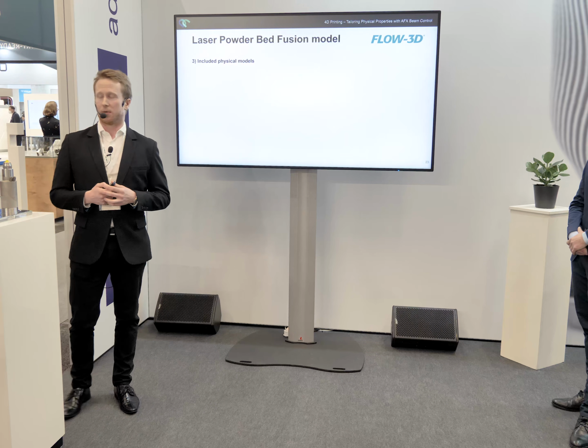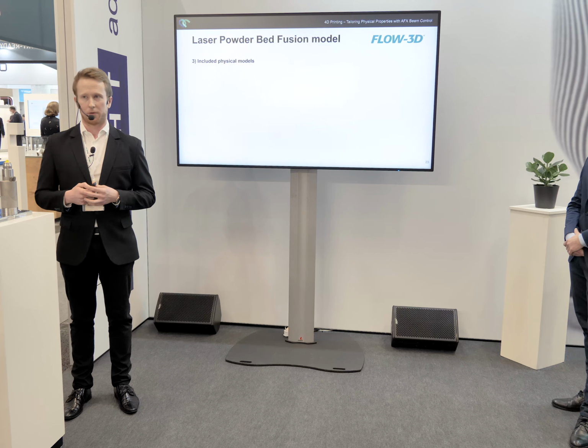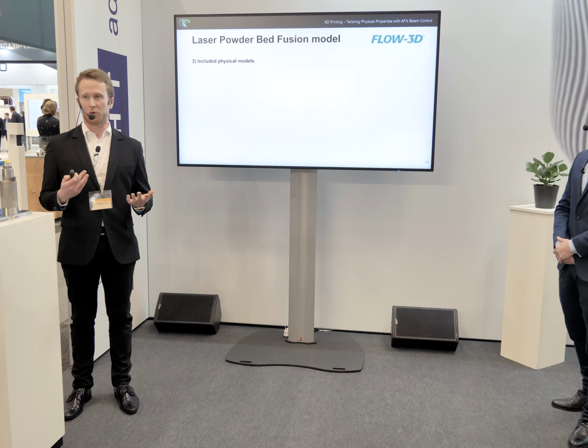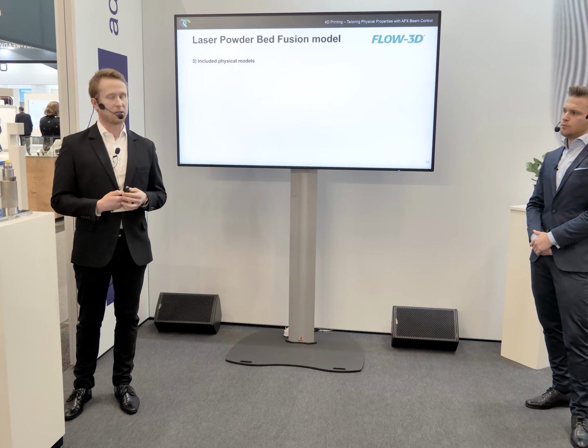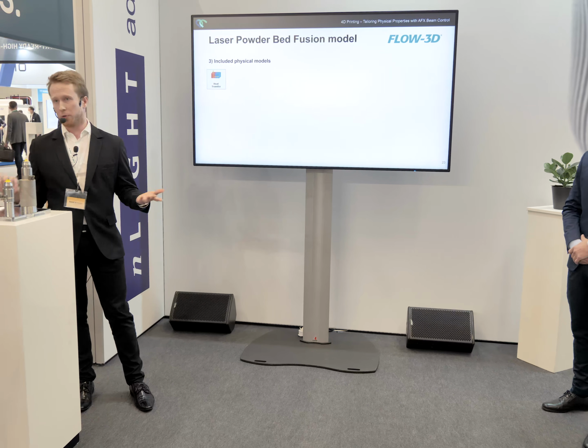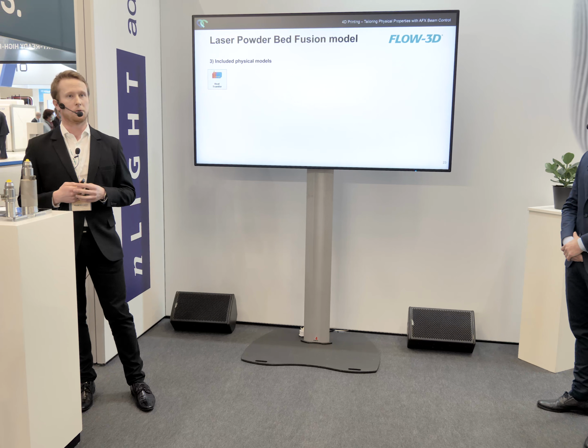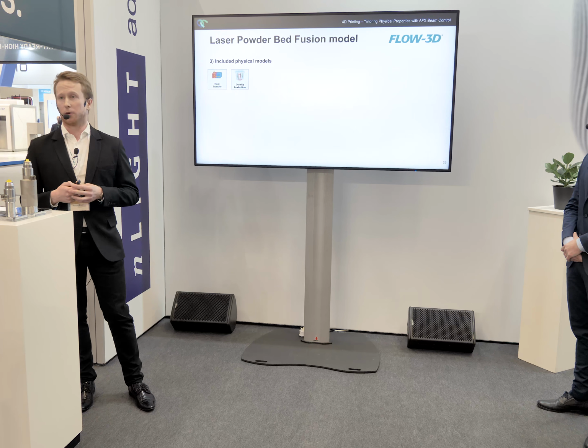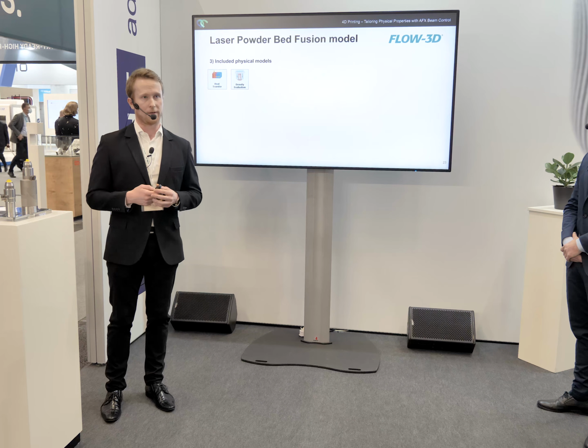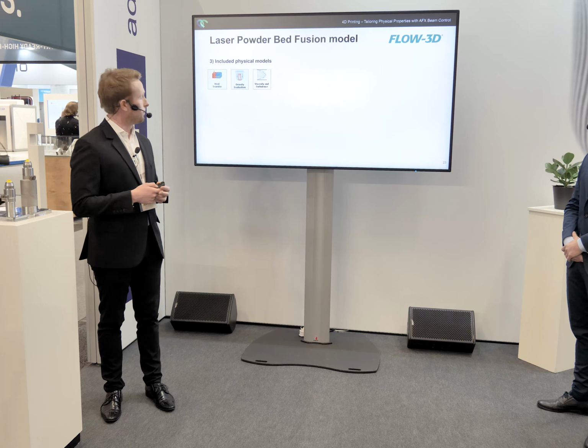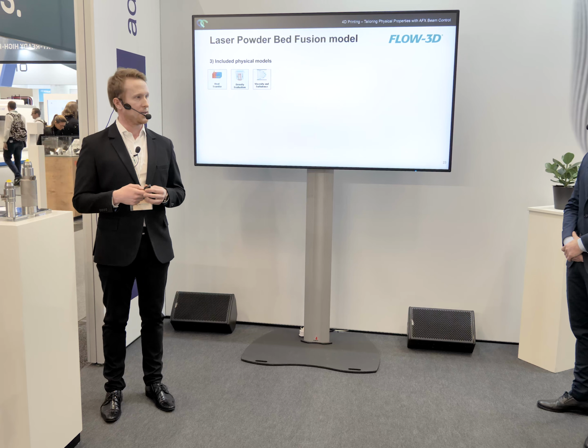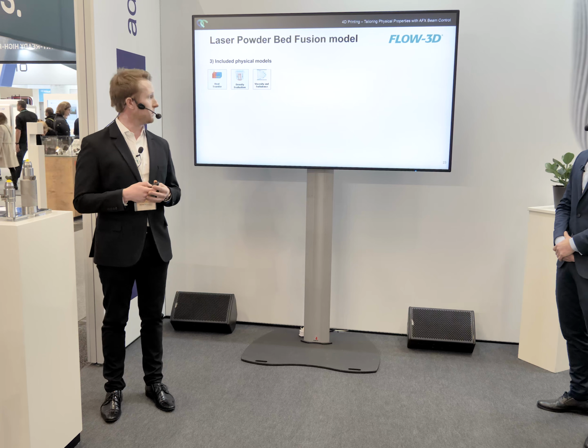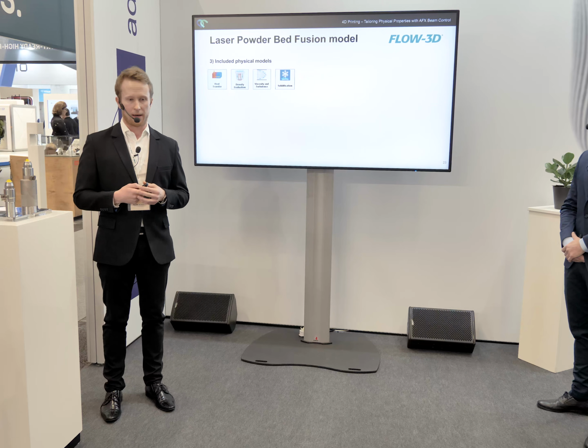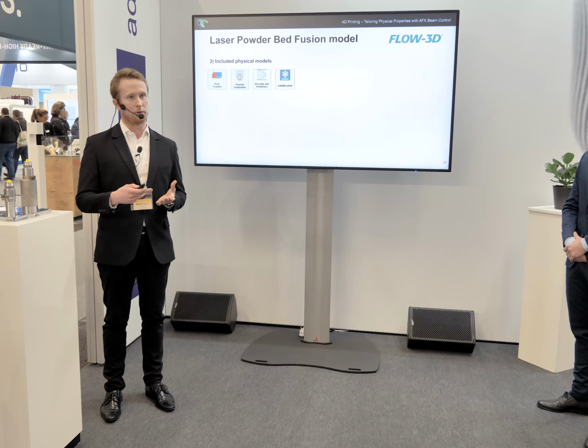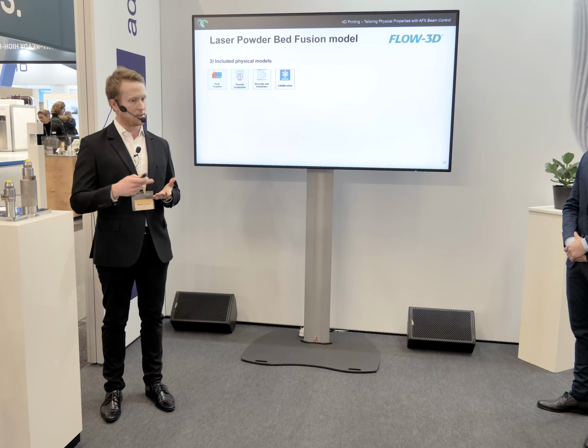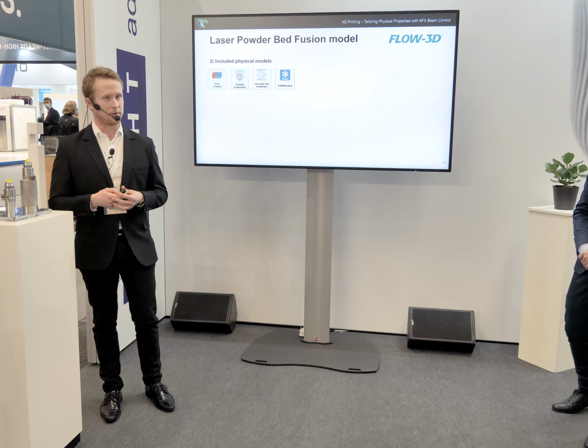Next step in setting up the simulation is to decide which of the physical models we would like to include, and that's also the beauty of CFD, that we can sometimes switch off part of the physics to see which of them is actually governing for the problem. So of course we do want to consider the heat transfer, which is basically telling the code to solve the energy equation. We evaluate the density as a function of the temperature to account for things like buoyancy-driven flows. The molten metal is approximated as a viscous fluid, and it flows in a laminar regime. The solidification model takes care of how the flow is resolved in the mushy region, where the fluid is between the solidus and the liquidus temperature.